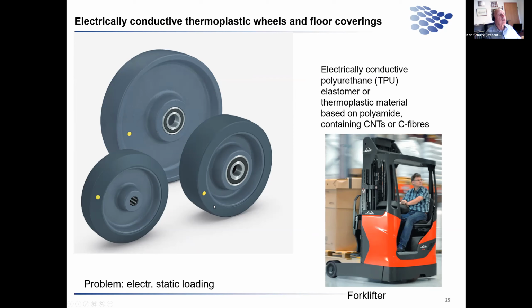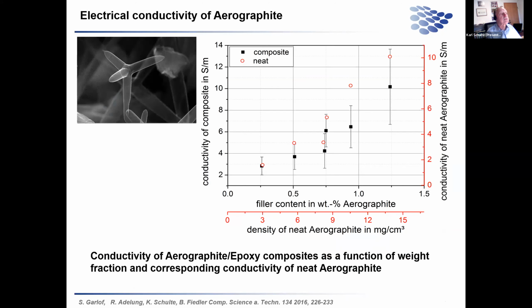So in these wheels, made of polyurethane, you add carbon nanotubes so they become electrically conductive. The floor itself has a cover of, for instance, polyamide, also containing carbon nanotubes, or recycled carbon fibers, and then you have conductivity and can get rid of the static charge. So that is one part of what can be shown here.